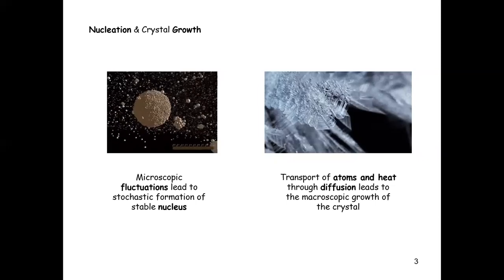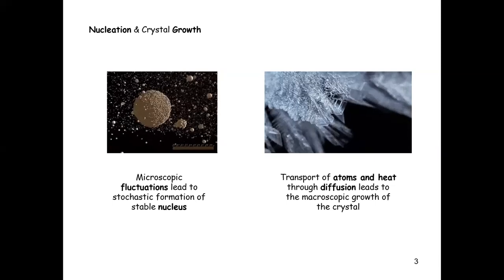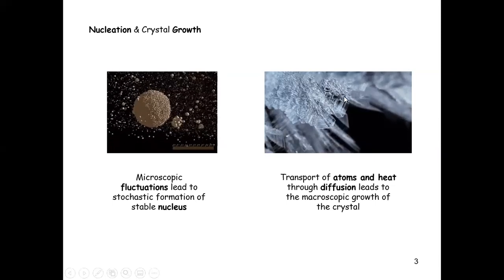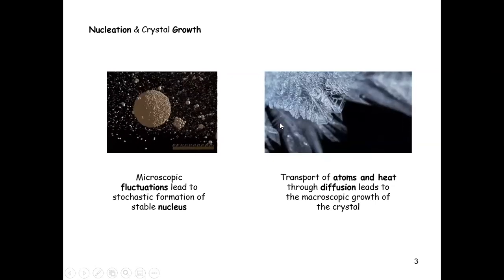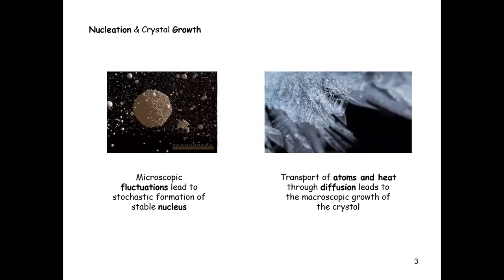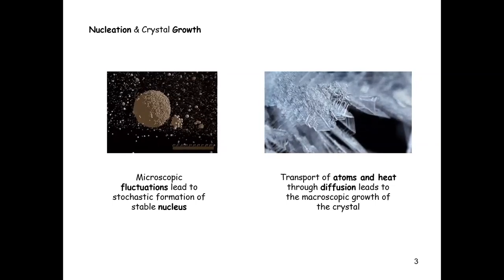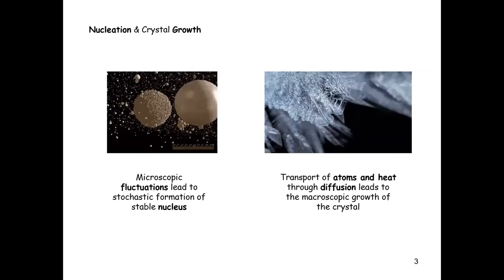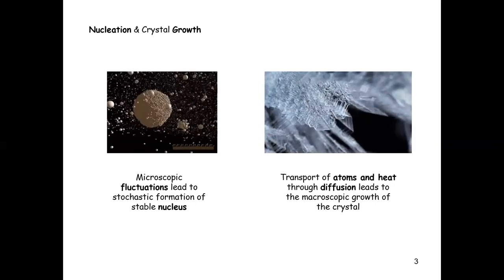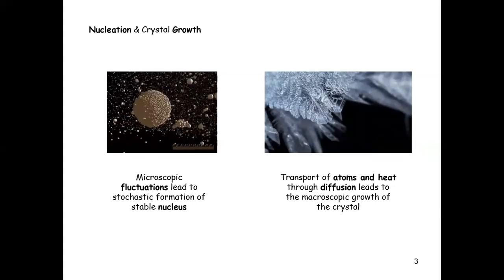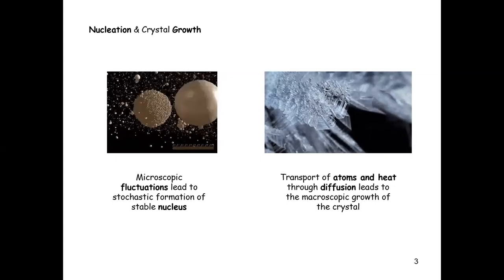Definitely not a spherical shape, but it has many different branches going through in all directions, like this one, or even here you see this branching type of growth. We call this dendritic growth. And why this tends to form dendrites is because of the Gibbs-Thompson effect. This is going to select a proper radius for the tip of this thing to further grow. So that's the overview for the topics.